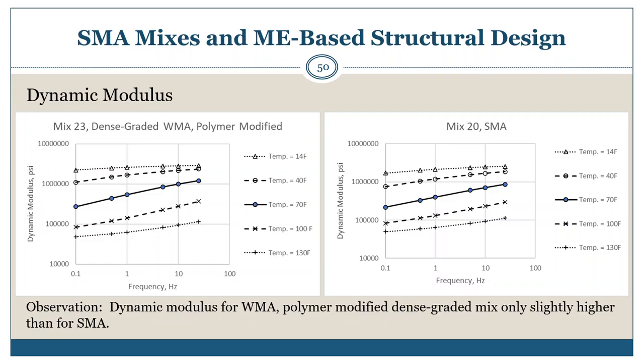Again, dynamic modulus values for SMA mixes can be higher or lower in comparison to conventional dense graded mixes because the dynamic modulus test is unconfined. For this example, the dynamic modulus values for the SMA mixes are slightly lower than for the conventional dense graded polymer modified warm mix asphalt.